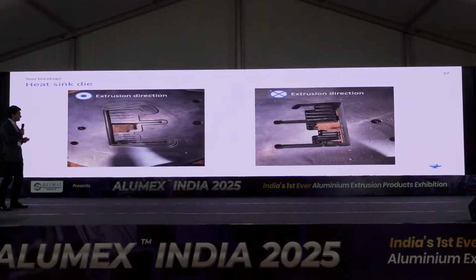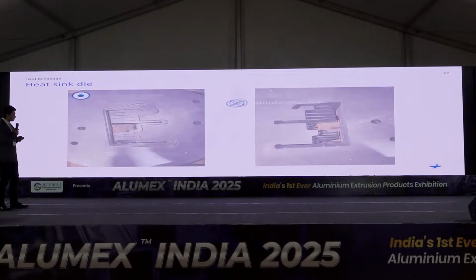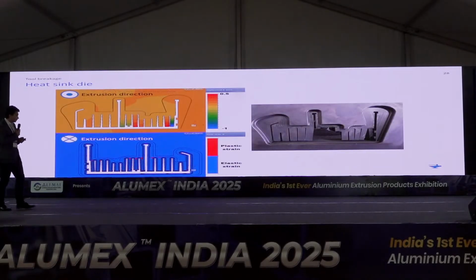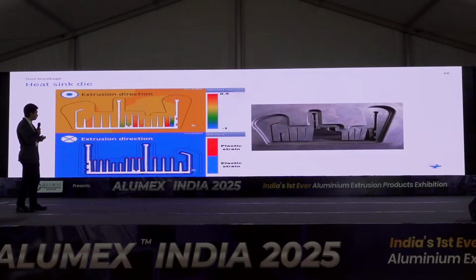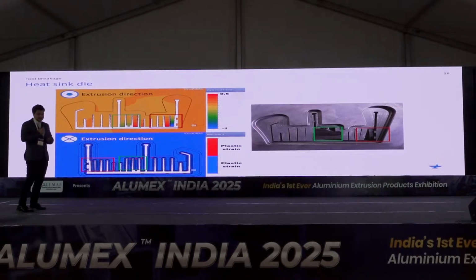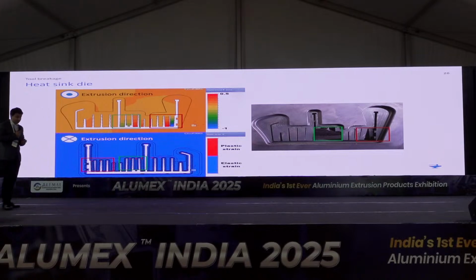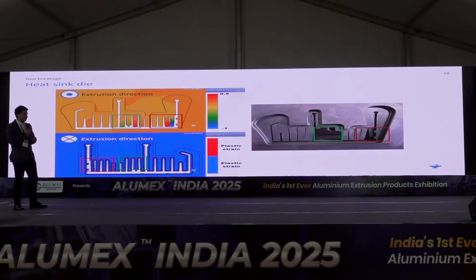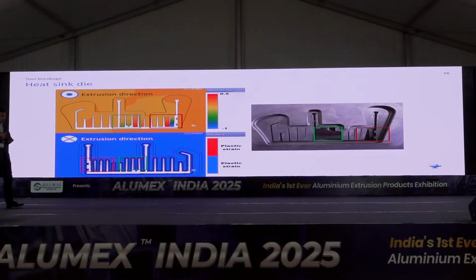Another example is a heat sink die. What happens? If we look deeper into the results analysis, we find two big problems. One is displacement, and another one is plastic deformation. Heat sink dies and heat sink designs are very unstable, and it's not that easy to create a good heat sink. It's very typical that they can break. And here you can see that with the simulation software, it's possible to predict it beforehand, rather than doing a very time-consuming trial.